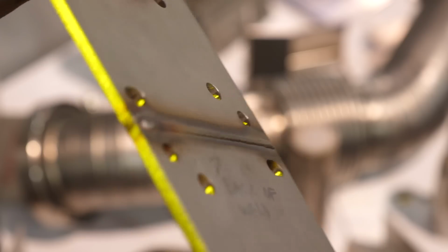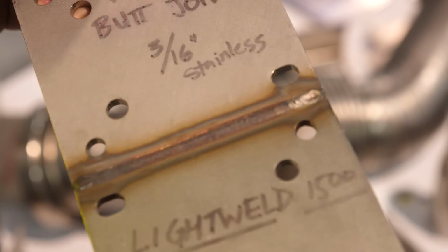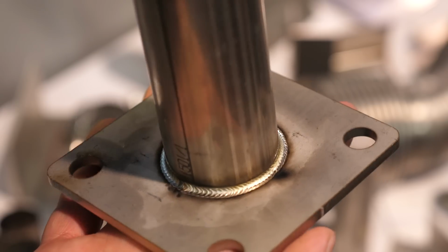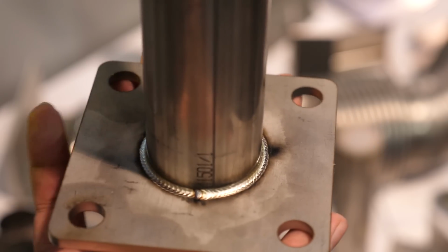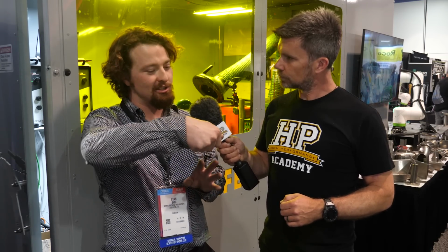So yes, the typical weld is very smooth and high speed. The stacked dime look, we actually found out by accident that it has the benefit of allowing us to go slower. So on really tricky applications such as rounding a pipe on a stainless steel exhaust, that pulse mode allows us to slow down and get finer control, and that's something that's been really beneficial to us.